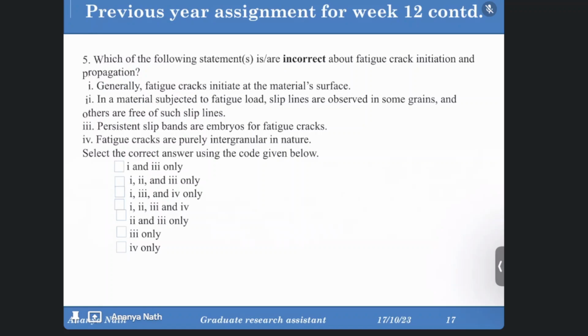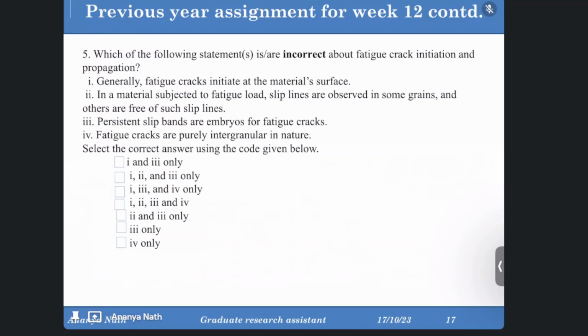Then, which of the following statements is or are incorrect about fatigue crack initiation and propagation? One, generally fatigue cracks initiate at the material surface. Two, in the material subjected to fatigue load, slip lines are observed in some grains and others are free of such slip lines. Three, persistent slip bands are embryos for fatigue cracks. Four, fatigue cracks are purely intergranular in nature. Ma'am, I guess the fourth one is incorrect. Yes, the fourth one is incorrect, but the rest are correct: generally fatigue cracks initiate at the metal surface.